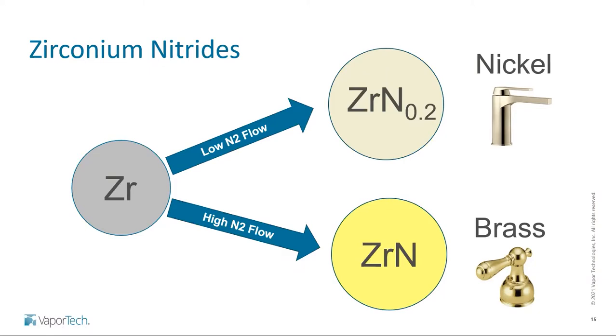So let's talk about zirconium nitride, widely used to make colors such as nickel and brass. So this is a little bit simplistic, but basically if you have a low amount of nitrogen that you're introducing into your chamber, you can form more of just a pale yellow nickel color. However, if you add a lot of nitrogen and you fully react your zirconium with nitrogen, it looks just like brass. And the 0.2 here just basically indicates that you don't have it fully reacted. This is where you have perhaps a solid solution of nitrogen in with the zirconium.